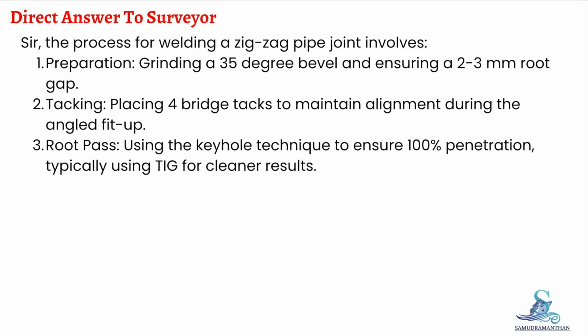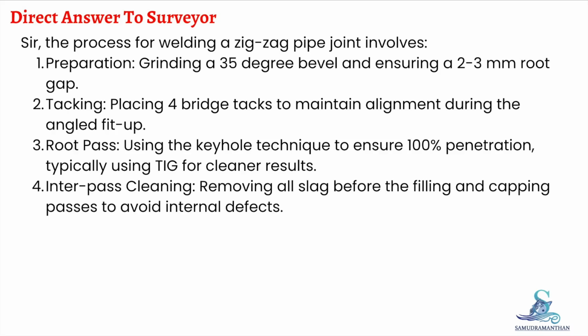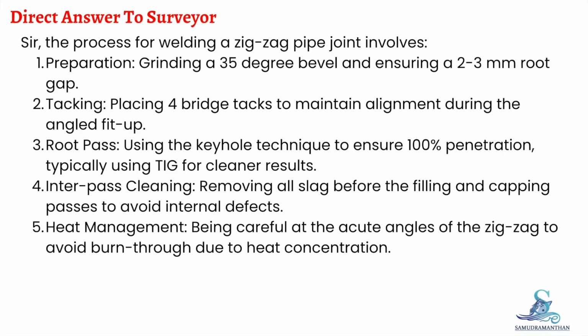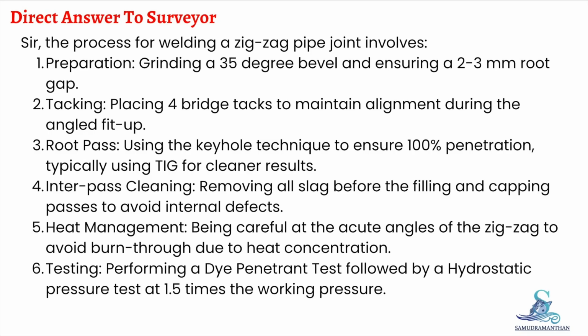Root pass, using the keyhole technique to ensure 100% penetration, typically using TIG for cleaner results. Interpass cleaning, removing all slag before the filling and capping passes to avoid internal defects. Heat management, being careful at the acute angles of the zigzag to avoid burn-through due to heat concentration. Testing, performing a dye penetrant test followed by a hydrostatic pressure test at 1.5 times the working pressure.